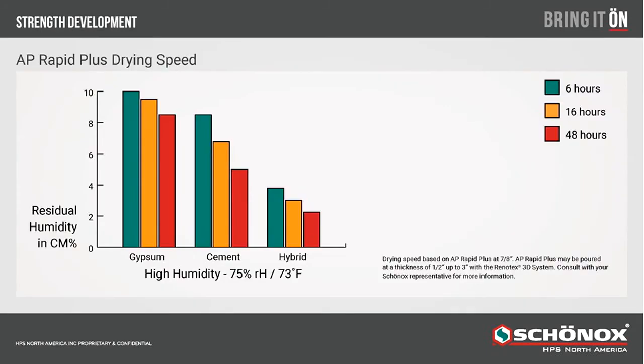So AP Rapid Plus, the drying speed on it, as you can see on this chart, is very quick. On a normal gypsum system, we're talking anywhere from 6 hours up to 48 hours, depending on the conditions, at 7/8 of an inch. Cement will dry a little bit faster, but our hybrids are actually getting faster than some of our traditional cementitious type products. So our product can be poured, AP Rapid Plus at 7/8 of an inch, and AP Rapid at a 1/2 inch. So we can get high strength gain and workability in a very short period of time.